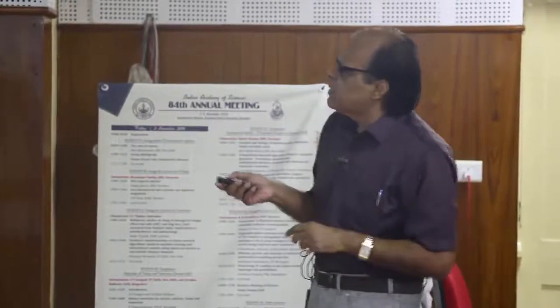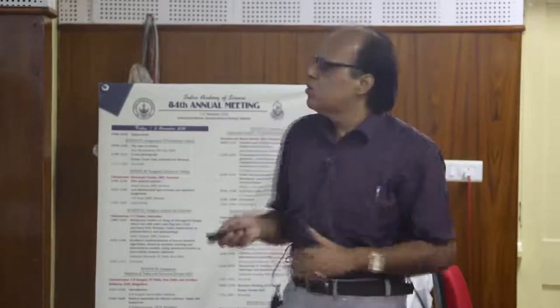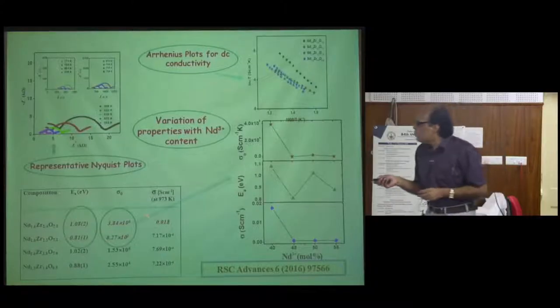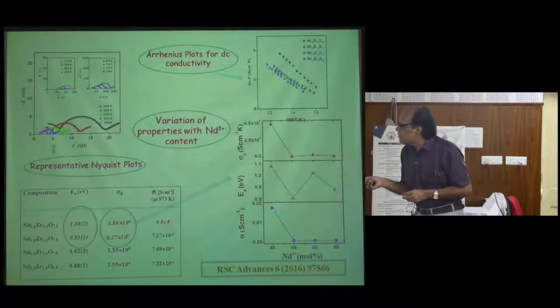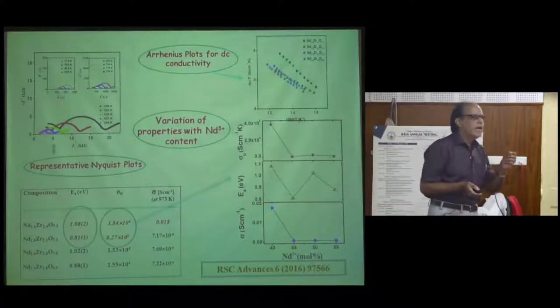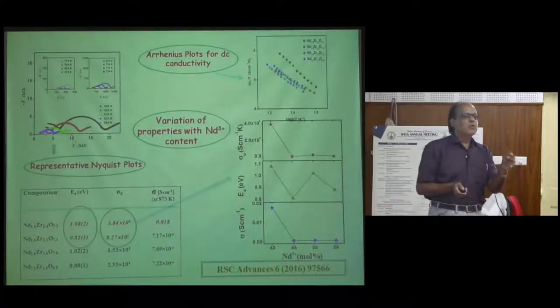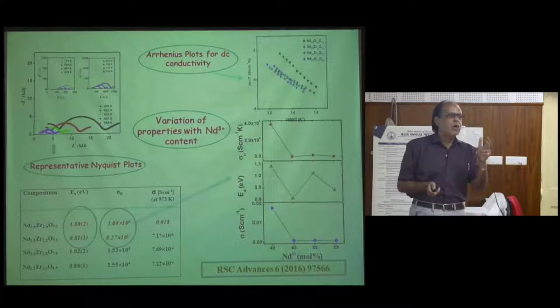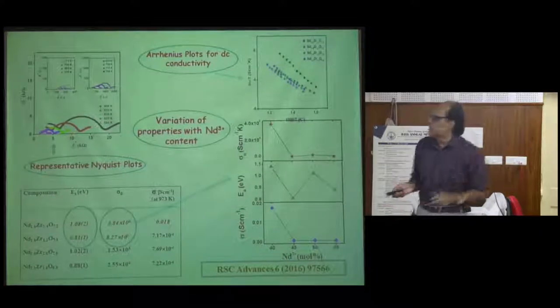Very recently, last year, we used one more approach based on anti-site formation. By anti-site formation in the pyrochlore structure, we could introduce considerable disorder as shown by XRD and Raman spectroscopy. And here is a compound which shows ionic conductivity at par with yttria-stabilized zirconia, but at 200°C lower temperature — with clear implications for SOFC technology.